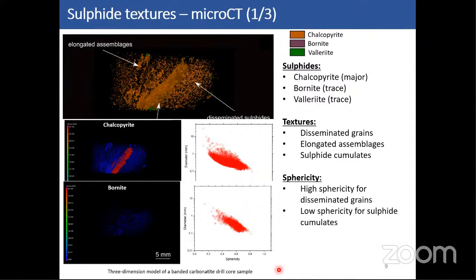Maybe the second point is that instead of one texture, which is disseminated sulfides, microCT showed the presence of three different ones. The first one is disseminated grains within the gangue, but the second and the third one haven't been observed with the microscope and mineral liberation analyzer. And these are elongated assemblages, as you can see here, and sulfide cumulates approximately 1 millimeter thick, in this case. Something which hasn't been observed at all before.